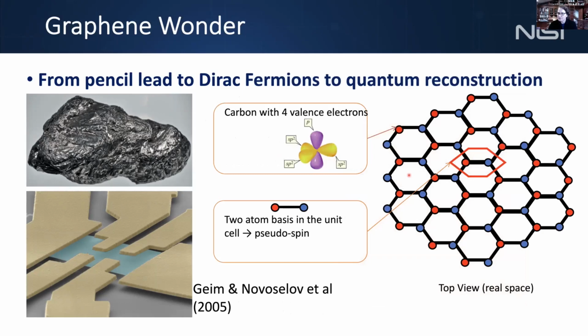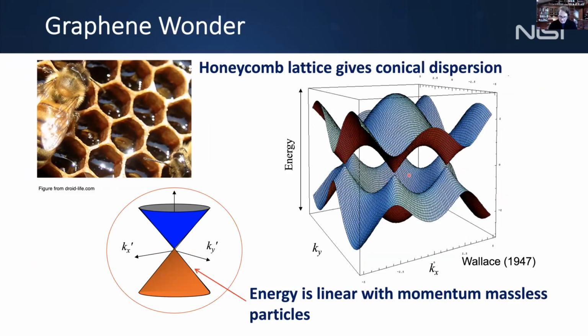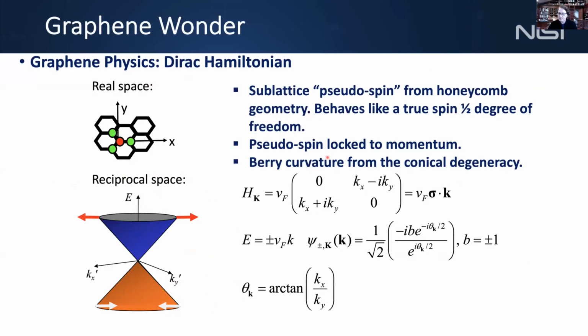Important things we need for this talk is that graphene has these two interlaced lattices, the AB sublattices. That gives rise to the pseudospin degree of freedom in graphene. And the other important part is that we have this linear dispersion at the K points. The last few things we need to know is that the pseudospin is locked to the momentum in graphene. That's an important point. And then that we have this Berry curvature at the Dirac point due to the conical